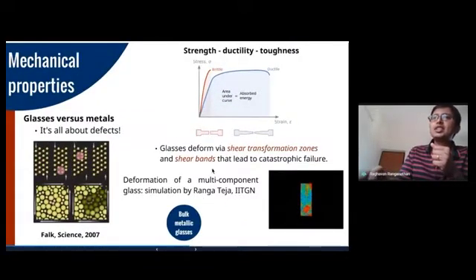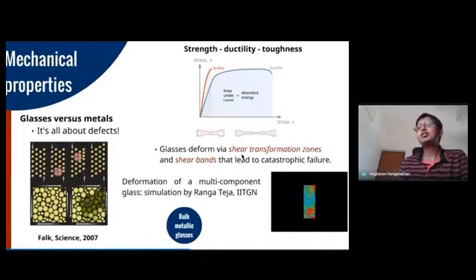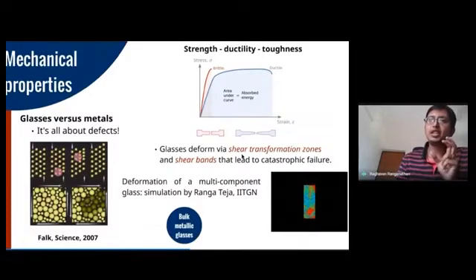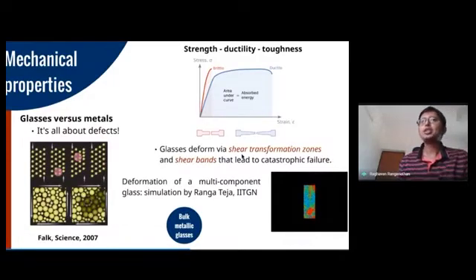And what's very interesting is these shear transformation zones, which are small, atomistically minute regions in the glass, they form small displacements. So all these atoms within the displacement zone essentially get transformed, and these grow in size and form what's called shear bands. So once the shear bands grow, this leads to catastrophic failure.